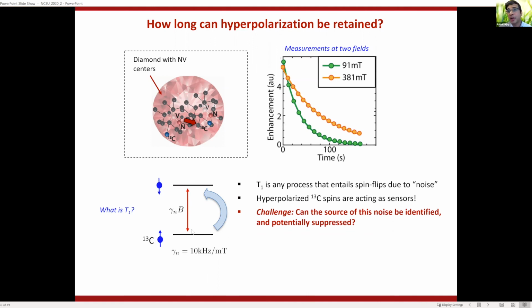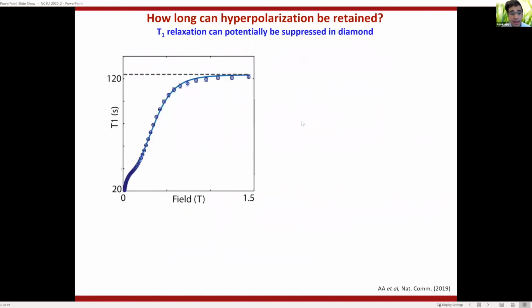Because you can hyperpolarize the spins, you can actually study T1 as a function of magnetic field. And we did this very carefully. This is a typical graph that you get. Different samples are different, but this is a graph in an enriched sample, so a large number of C13s. This is T1 as a function of magnetic field, and you can see that it's got a very special shape. It's got a shape of a knee, almost like a step function.